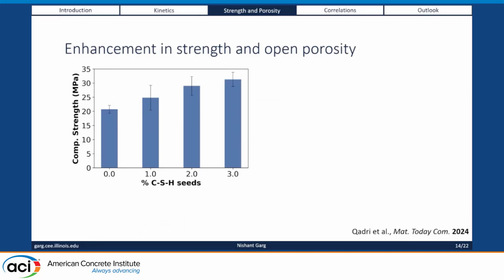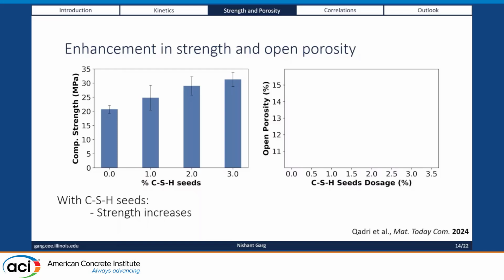If you look at the compressive strength, again, generally we see an increase depending on the dosage. The other thing I wanted to look at is the porosity. There's a lot of strength data in the literature, but not much data on porosity and durability. There we find that the porosity also goes down by a few percent as measured by helium pycnometry. After a dosage of about 1 to 1.5%, everything plateaus. So the gains in porosity become marginal at some point, even though there is an increase in strength. So that's something to consider.